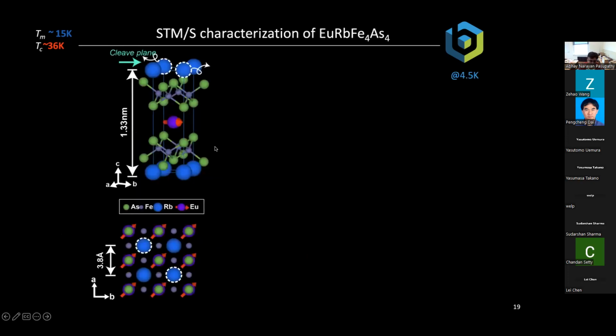Okay, so what do we do in our experiment? We're doing scanning tunneling microscopy. So what we do is we take a single crystal of this material and we cleave it in vacuum. So we just break the surface. And when you do that, 90% of the time, the place where the material breaks is on this rubidium layer. That just is the most natural place for it to cleave. And so what is exposed is the rubidium layer, and below the rubidium layer is the iron arsenic layer, which is a superconducting layer. And below that iron arsenic layer is the magnetic layer.